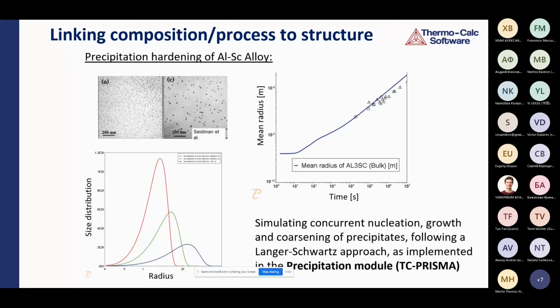I will show you an example that relates to predicting the resulting structure. So this is an aluminum scandium alloy that obtains its strength from the scandium-rich precipitates. These precipitates will nucleate, grow, and eventually coarsen during the aging step. So we can see this from the micrographs as well, but also the simulation results in the figure. So it's important to be able to predict the amount of precipitates and also their size, since this relates to the strengthening of the alloy.